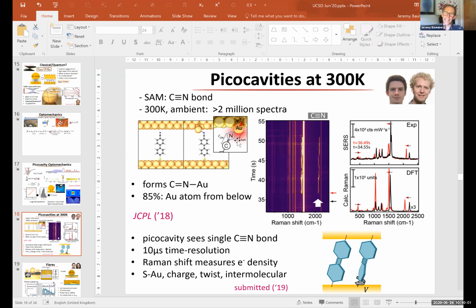So all we do is we look at the data, and it sort of tells us that this is what has to be going on. What we can also do is power-dependent measurements and temperature-dependent measurements, and it shows the probability of creating this. We can see it is thermally, I mean, actually we're driving it, and it gives you the energy for doing this. And that energy is exactly what you expect from what people have measured for the add-atom energy of gold. And we've also done it for silver, and it matches the add-atom energy for silver. So from all these measurements, we're fairly happy that what we see here is just a single gold add-atom. Now, if I raise the power, I can see a second one appear, but the second one may be at a different distance here, so that mode appears down here.